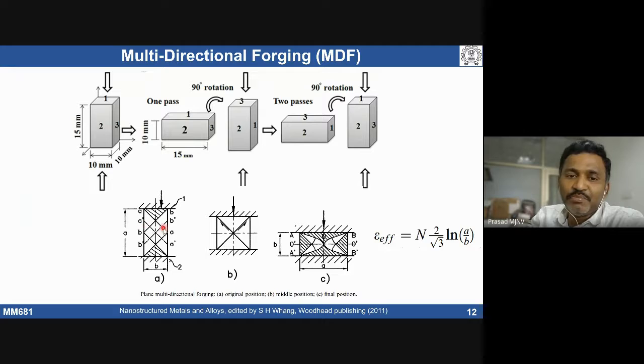So it's basically a simple compression. By compression we are inducing a large amount of strain in the material, and when you rotate it every time, you change the path of the deformation, so internally the microstructure undergoes such metal flow. When you change the metal flow in all directions, that can lead to a fine grain size in the material. There are various methods available; people have developed more than 100 methods under the SPD technique. The most important ones I discussed are ECAP, HPT, accumulated roll bonding, RCS, and MDF, multidirectional forging.